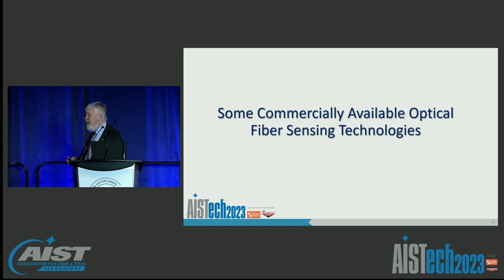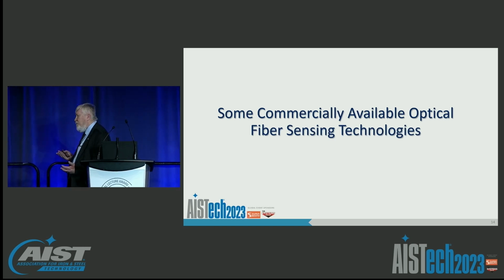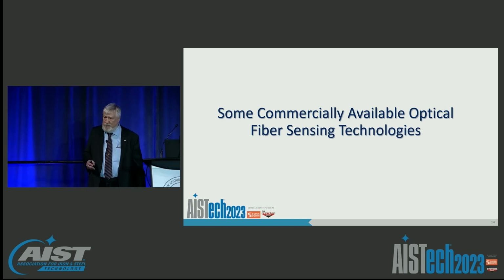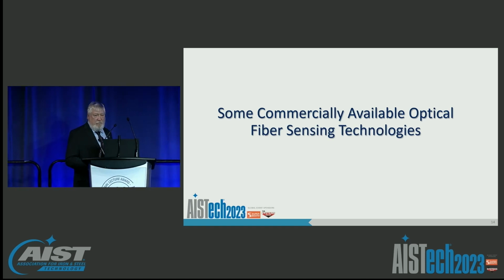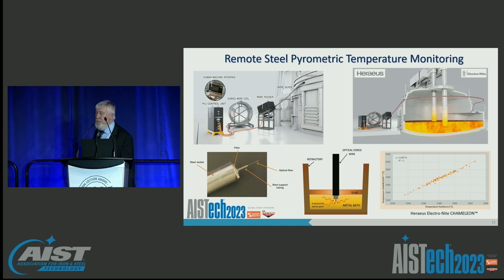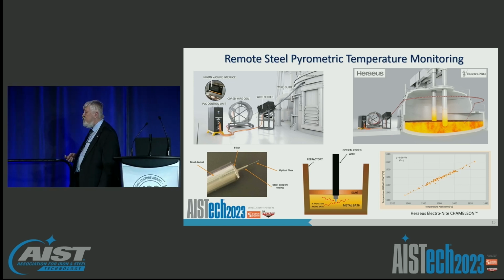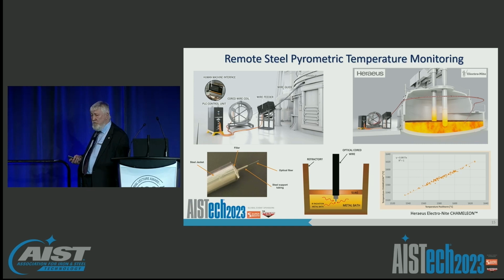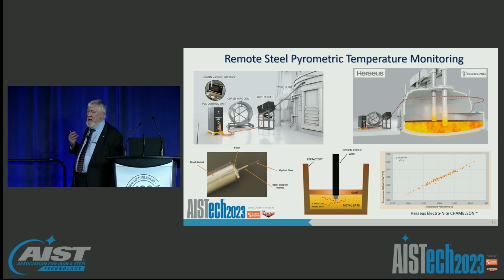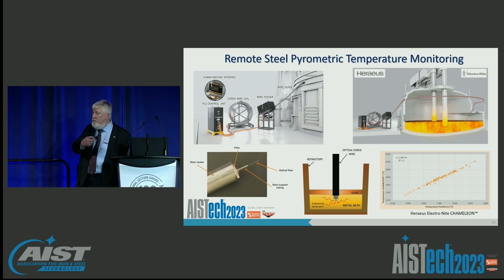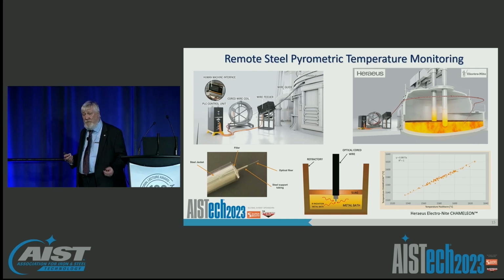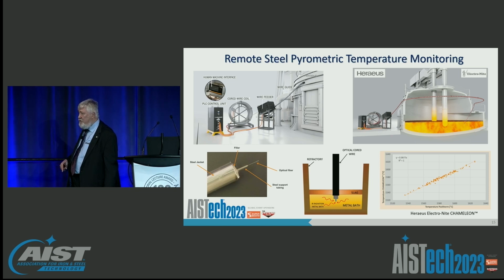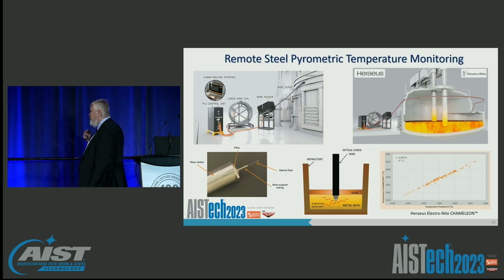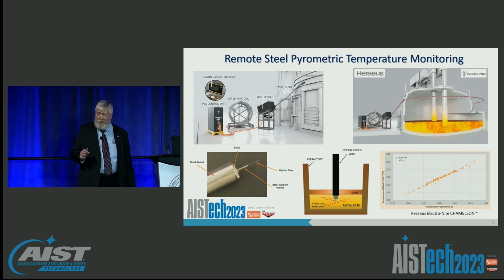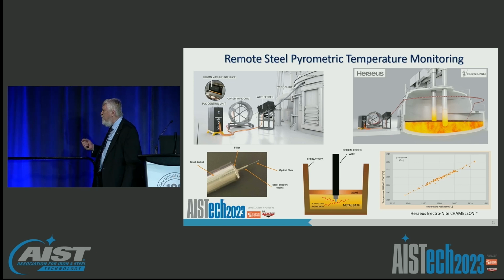So I want to now just talk a little bit about how we use some of these fibers. And today, some of these fiber systems are already being introduced into the industry for a lot of uses. And just to give you a few examples, here's a system that is the Chameleon system by Heraeus Electro-Nite. And it is actually a consumable fiber that is injected into the steelmaking environment, the EAF or LMF environment. The fiber is consumable, it's protected and jacketed, and it actually measures the thermal emission and carries it back through the fiber to measure, essentially through an optical pyrometry method, the temperature at the tip of the fiber being introduced and ultimately consumed. The beauty of this method is that the tip of that fiber actually acts as a black body radiator, and so emissivity corrections aren't required, and so you can get a very accurate temperature measurement.